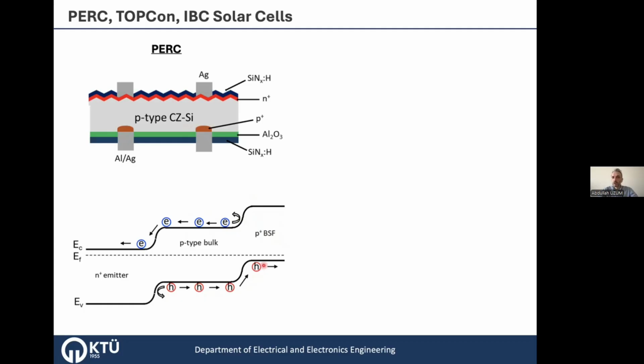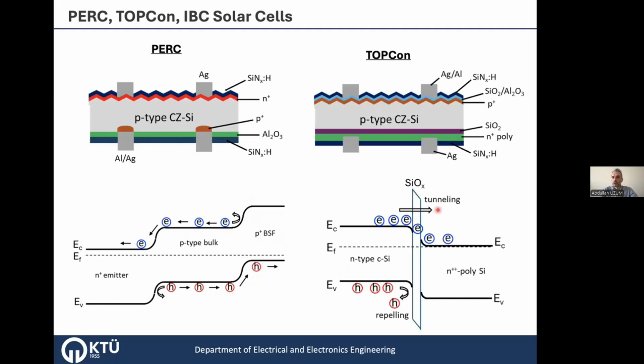And in the TOPCon structure, we have a very thin silicon dioxide tunneling layer. It is very thin, and it also has a passivation effect. And thanks to the thickness of it, it can allow quantum tunneling, and then electrons can tunnel through the layer. And with the help of the heavily doped N side on the back, you have the barrier like this, and holes are repelled. So you can also avoid the recombination here.